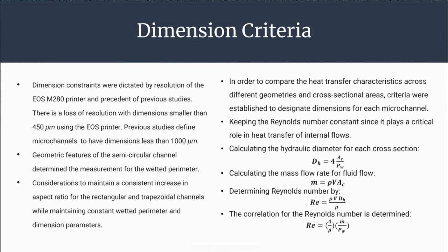Beyond that, some geometric features of the semicircular channel would determine the measurement for the wetted perimeter. Essentially, the wetted perimeter for the semicircular was always going to be the largest. So we had to play a little bit of a puzzle, trying to fit within these criteria of a lower range of 450 microns and an upper range of 1,000 microns, and hit the same wetted perimeter for all different shapes. This would lead to different hydraulic diameters, but as long as we're keeping the mass flow rate and the wetted perimeter the same, we were trying to maintain a constant Reynolds number.